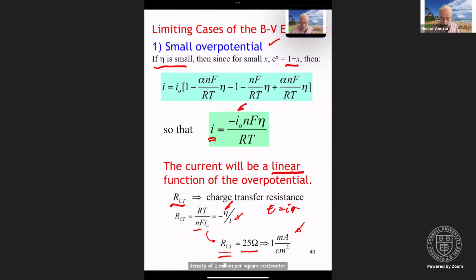Depending on the application, this can be either large or small. If you're working on, let's say, fuel cells, that's an intolerably large overpotential since you're trying to drive amps of current. If you have 25 ohms, then you basically are dropping volts of potential in your cell. On the other hand, if you're looking at kinetics of charge transfer in a homogeneous system with dissolved intermediates, that's much more tolerable. And so it depends on the experiment that you're doing and the current densities that you're applying.